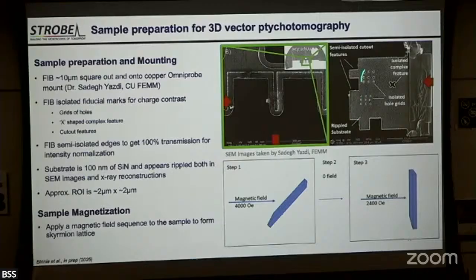nanofab, and then stuck this onto a finder grid, and then stuck that into the coherent microscope. Then we applied the magnetization. This was again during COVID, so it's not perfect, but we don't need perfect skyrmions to see if we can image them. We were happy enough to have even imperfect skyrmions, because then we can see what texture we can see. These are dipole-stabilized skyrmions because they had to survive without a magnetic field, because there was no magnetic field available in the microscope.